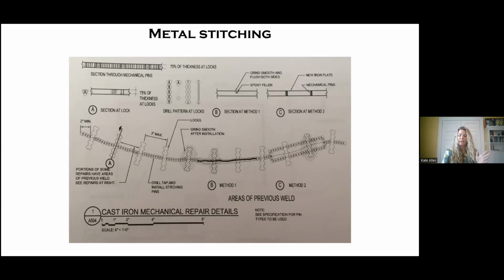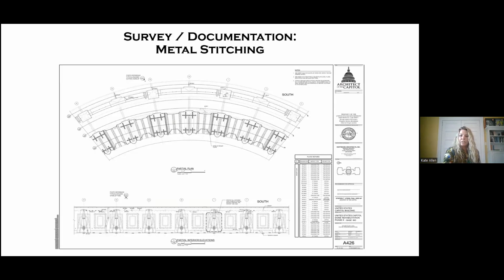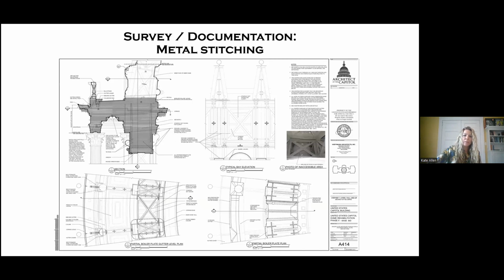So you think about that on 3/8 inch cast iron. We had 12,800 inches of cracks at the US Capitol Dome. So it was a very slow process. This is just showing some of the metal stitching from the dome. There were cracks not only in both of the interior and exterior domes, but also the boiler plate, which is the area beneath the balustrade.